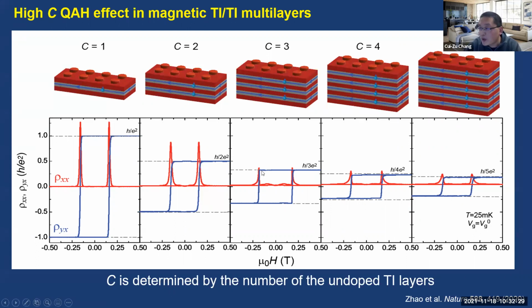If you take a careful look here, you can see that when you increase the Chern number, the longitudinal resistance actually goes higher. In my opinion, there are two possibilities. One is just the intrinsic property. You know, there are side surface effects, and the side surface affects this finite longitudinal resistance here. And there is another possibility, it's just the growth problem. When you grow a very thin topological insulator film or magnetic topological insulator film, it's very difficult to avoid the introduction of impurities or defects in the growth.